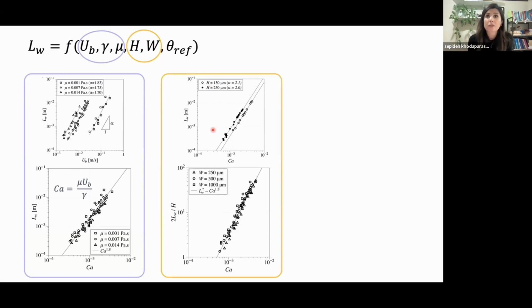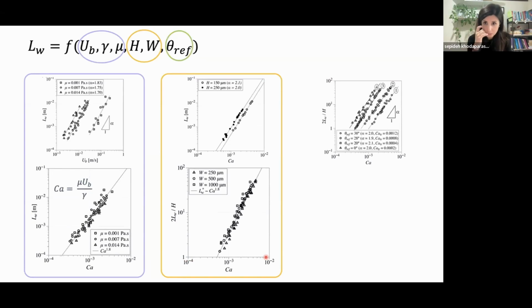But for different width of the channel, if I non-dimensionalize the wetted region over the height of the channel, you see that again, all of the data collapses onto one single curve. So we have established at this point that the y-axis should be L_W, the wetted zone over the height of the channel, or 2 times the height, or half of the height of the channel. And the x-axis should be some sort of a capillary number.